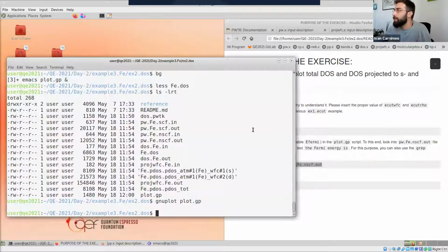And then the following question is, should we do the K-point convergence, ecut convergence, before or after VC-relax, starting from the experimental structure? So I think that in this particular case, the answer is relatively simple. For example, we treated silicon and we treated iron, and we treated aluminum. So as far as K-points are concerned, if you take an experimental lattice parameter and you do a K-point test, I think that will do. Of course, the true lattice parameter will be a bit different, but I don't think this will change.